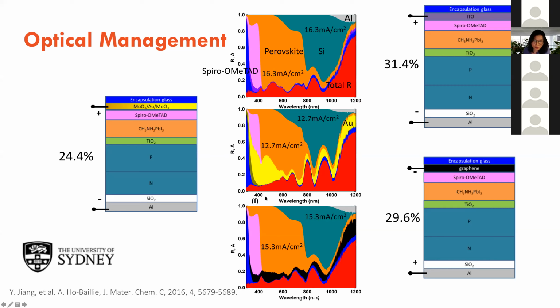And you can see in all 3 cases, the spiro is very absorptive of the short wavelength, so around the UV range, which is annoying. And it's sitting on the very top of the cell. So like, you know, people have skin cancer because the skin absorbs the UV light on the surface very well. So what do you do? Well, you can replace the spiro with something that is less absorptive.